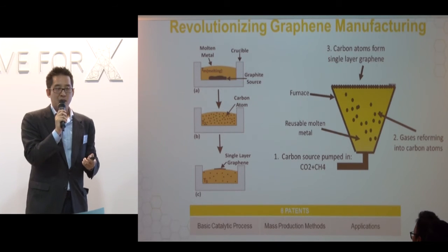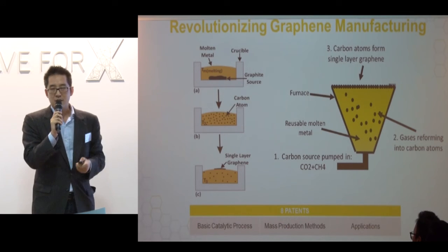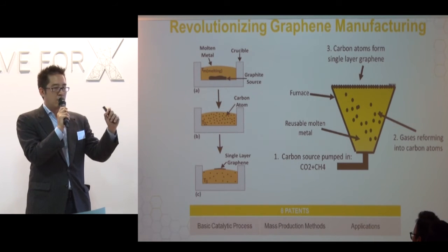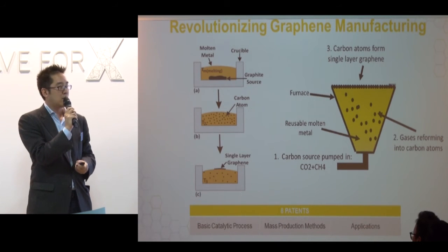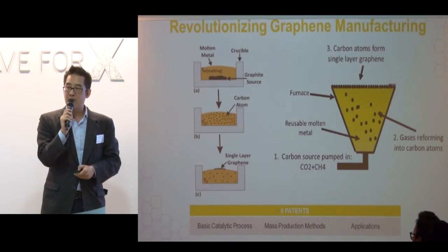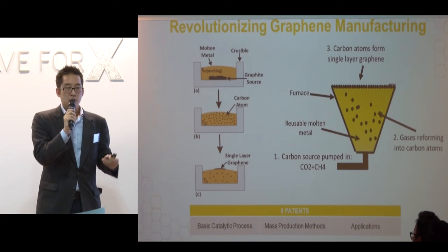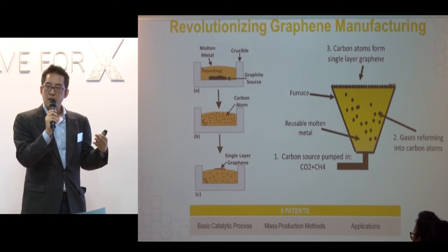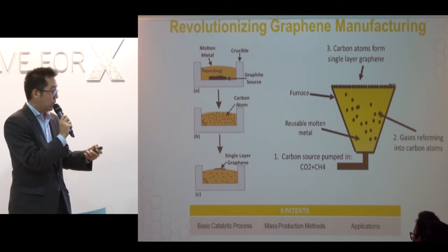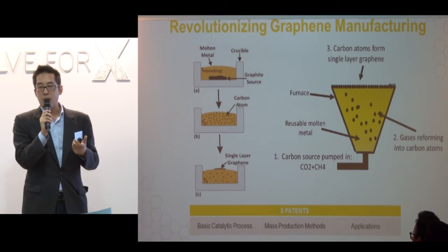And this has been verified. We've taken samples, refuse from the steelmaking process, and we've identified that there is in fact graphene content, although it's very dirty. So if we modified this equipment, then we can do this on a grand scale. And in fact, we're kind of agnostic to the carbon source.